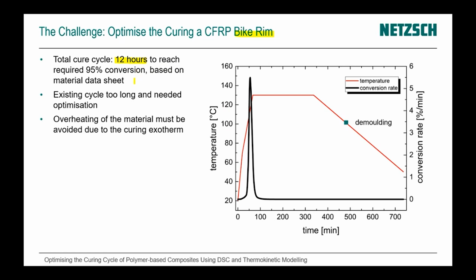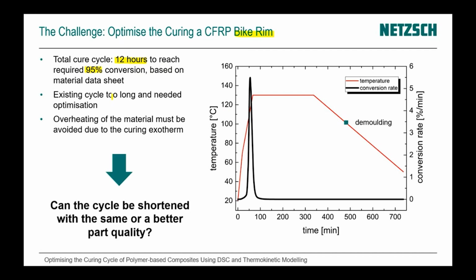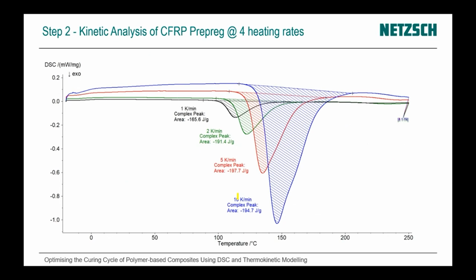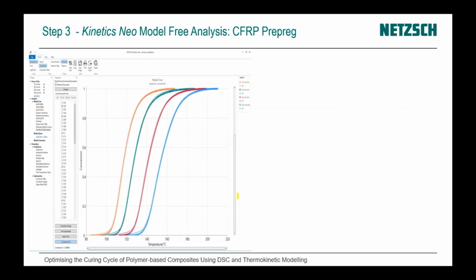And finally, in order to get 95% of conversion, it was too long. The question is, could it be shorter to get the same or better part quality? The red curve is a temperature for industrial cycle, and the black curve is our curing curve. Now we have measurements at different heating rates. Then we apply our kinetic modeling for this data.